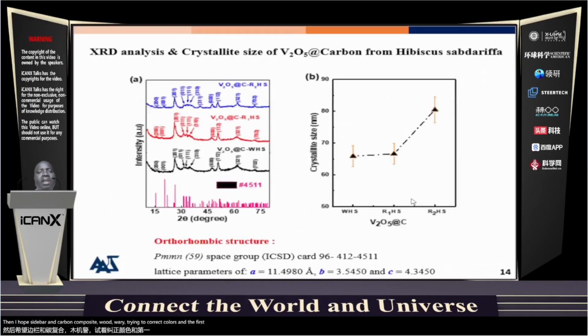The first characterization that we have done is to look at the structure of the material that we produce from this hibiscus sabdariffa. Figure A that I'm showing is the X-ray diffraction using the three different hibiscus sabdariffa: the white one, the light red, and the dark red. We could see that we still have the vanadium pentoxide, while the carbon aspect is not appearing here, but we'll see that it appears in the following characterization.